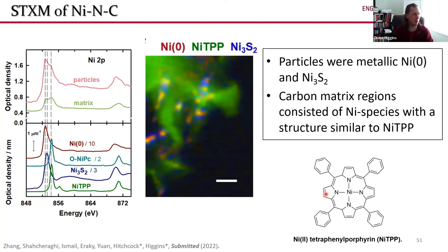And so what we found that was very interesting is, first off, not the biggest surprise, the particles were found to be metallic nickel with a bunch of nickel sulfide in and around them. But the really interesting thing is that these carbon matrix regions, everywhere that we looked at these carbon matrix regions, they had these nickel-like species present within them with a spectra that most closely resembled the nickel TPP structure. So this kind of painted a slightly different picture from what I showed previously, where the nickel phthalocyanine active site structures seem to have properties somewhat similar to those, but structures that more closely resembled this nickel TPP-like structure.